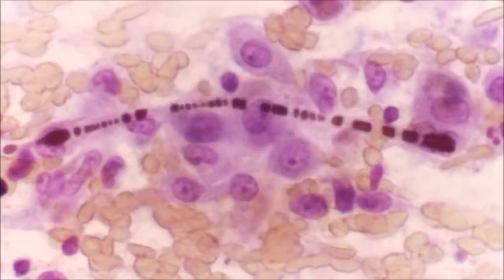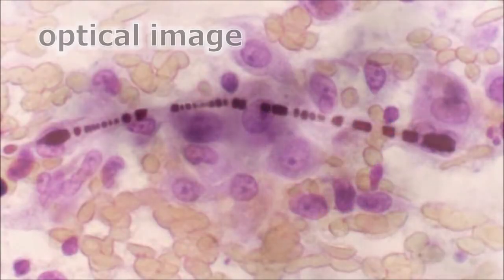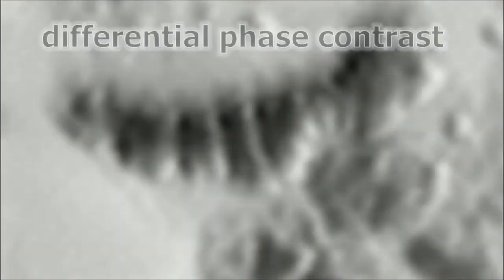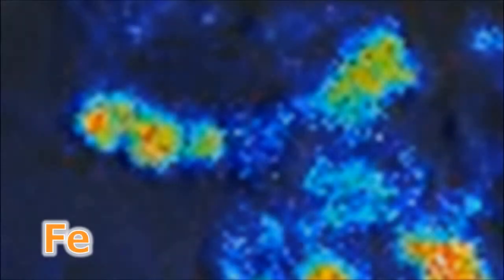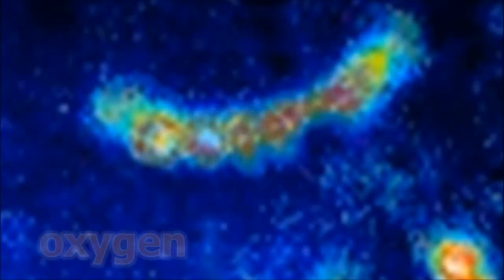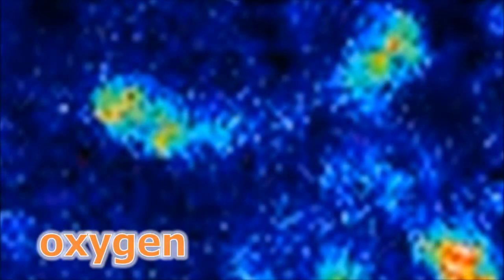Low-energy X-ray fluorescence allowed us to identify subcellular distribution of physiologically important elements such as zinc, iron, sodium, magnesium, aluminium, silicon and phosphorus. Recently, the combination of low-energy X-ray fluorescence and microimaging revealed unexpected formation mechanisms of asbestos bodies in lung tissues by analyzing the correlation of magnesium and iron in combination with lighter elements, in particular oxygen.